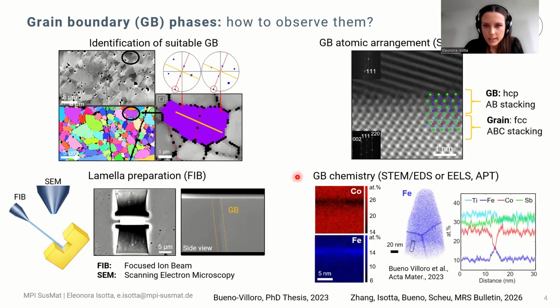Another thing we can characterize at high resolution is the chemistry of the grain boundary, which can be done using energy dispersive spectroscopy in STEM mode, also on a lamella. Alternatively, one can use electron energy loss spectroscopy. Another method for achieving high chemical resolution is atom probe tomography. This requires preparation of a different type of specimen, which has a tip shape, but allows very high sensitivity and very high spatial resolution.